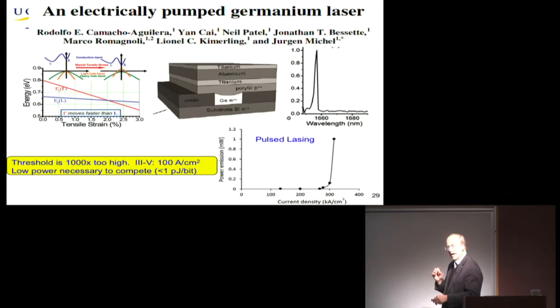So again, it may not be calibrated, but 300 kiloamp per square centimeter is 1,000 times higher than where we are today with epitaxial growth on silicon, or more than 1,000 times higher than where Infinera and Lumentum are with an indium phosphide laser. So it just doesn't play. It doesn't work because in these transceivers, power is the big issue. And the total power budget has to be 3.5 watts, say, for one of those packages I showed. And that means the laser thresholds have to be down 10 or 20 milliamps, not amps.